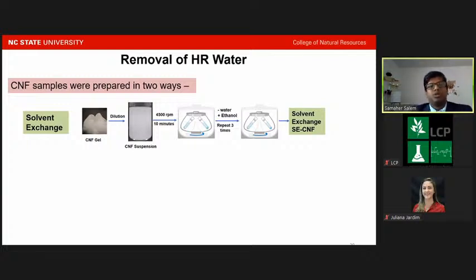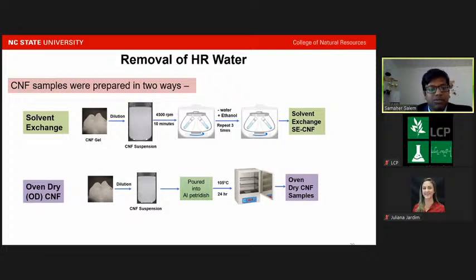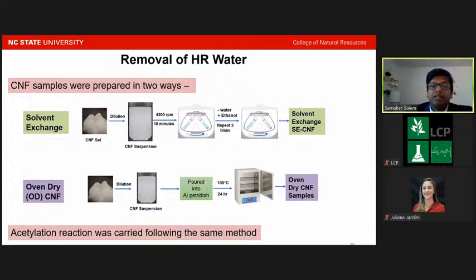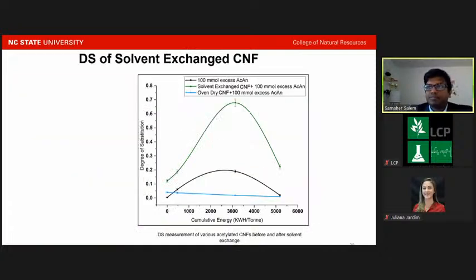So further to confirm this trend, we prepared the nanocellulose samples in two ways. One is the solvent exchange way, where we took the nanocellulose and used ethanol to remove the water using the centrifuge method, and we produced solvent exchange CNF. And in the other case, we oven-dried the CNF at 105 degrees Celsius for 24 hours and produced the oven-dry nanocellulose samples. And then we did the acetylation reactions following the same method. Here is the data for the degree of substitution, which we measured after the acetylation of those samples.